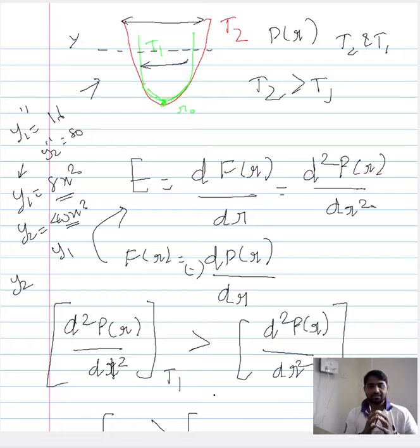We saw that the first derivative of the force relates to the elongation, or the Young's modulus that we see in the stress strain curve in the macroscopic scale. Based on that understanding, we saw that the slope of the force curve translates to the Young's modulus, and any movement away from the equilibrium position that happens because of the increase in temperature would mean a decrease in the slope, and that would ultimately mean that Young's modulus decreases. So this is our understanding from the force curve.